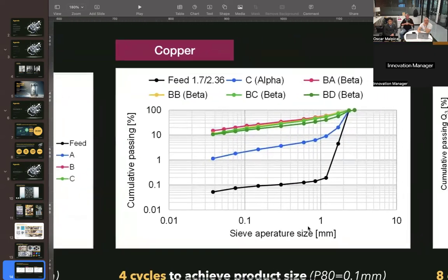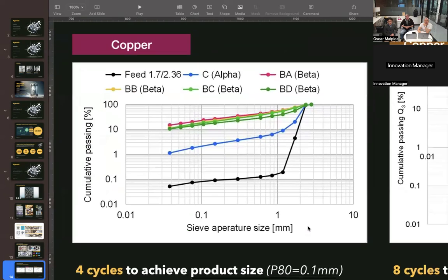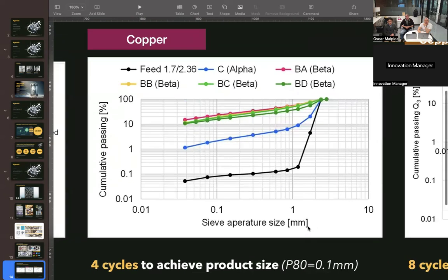And then the next chart is a copper example. In this example, we've got the black line again showing the feed. The feed was actually 1.7 to 2.36 millimeter. It tapers off because the sieving itself produces some small amount of fine fraction. So you can ignore that long tail on the black line there.